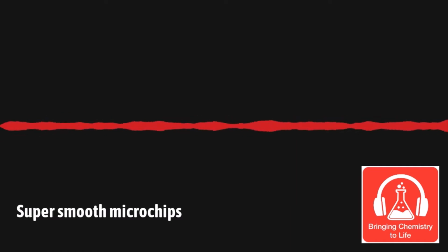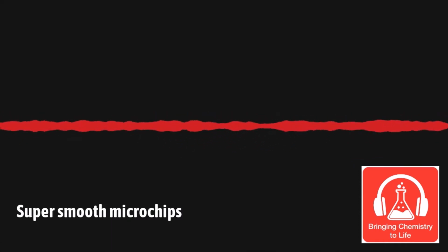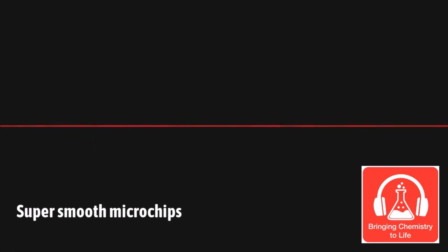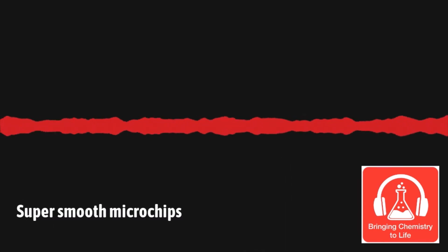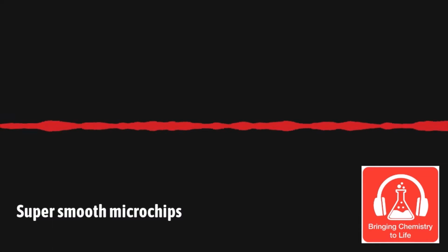It's interesting. And I have a very naive question, perhaps. What happens to the particles when you remove them from the microchip? Because I assume they can interfere with the polishing process as it carries on. Yeah, so during the polishing process, a fresh slurry stream is flowed underneath the wafer in the polishing pad. The slurry basically flows off the platen into a waste stream, right? And after the polishing process, the wafer is removed from that pad surface, and there's usually a high pressure rinse, and that wafer undergoes a post CMP cleaning procedure to make sure that all the particle residue and chemistry is removed from the surface.